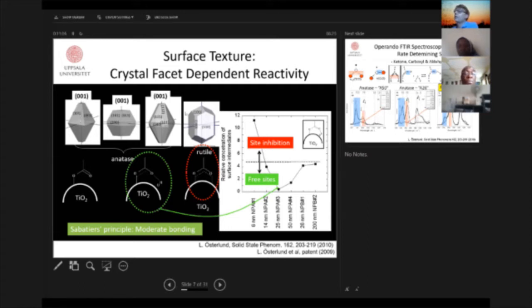You can cut it in different forms, and you can do it synthetically. As it happens, when you start to moderate with this texture of the crystal, you can actually moderate the amount of these strongly bonded intermediates in a typical reaction. And this is shown on the right-hand side here. Depending on how you cleave the crystal and the facets which are exposed, you can either get it very quickly poisoned, or you can have a sustained activity.